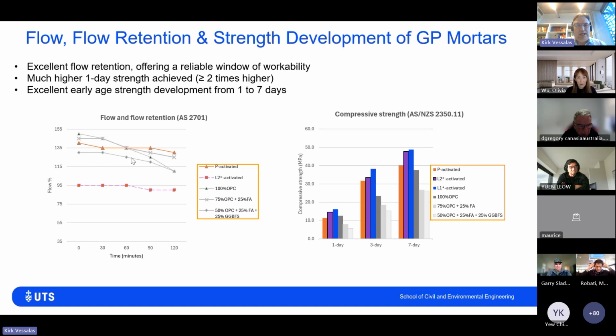But if you look at the powder activated system and the liquid activated system, the retention is very, very good. If we compare against conventional 100% Portland cement, shrinkage limited cement systems, and our binary and ternary blends, you can see we actually do get a loss in retention. So the retention of the geopolymer system is very, very good in comparison to the conventional system.